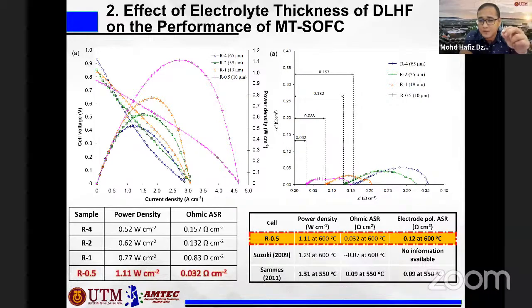Since we use a very good conductive anode, because we use nickel, the conductivity is like 10,000 or more. For the cathode we also use a perovskite structure, which is a very good electron conductive material. So the only one that gives a high resistance is the electrolyte. If you have a multilayer, you have to know which component has the highest resistance, because normally the highest resistance will dominate the ohmic resistance reading. For our case, the electrolyte will give the highest resistance because its conductivity is much, much lower compared to the anode and cathode. Therefore we look at the ohmic resistance here. The first intercept is the ohmic resistance.